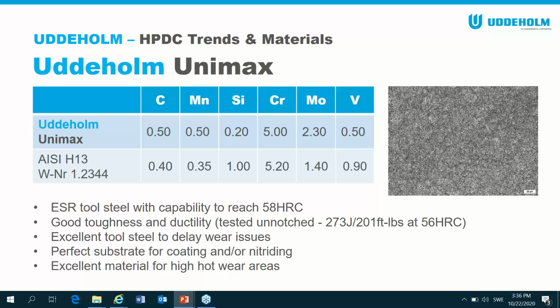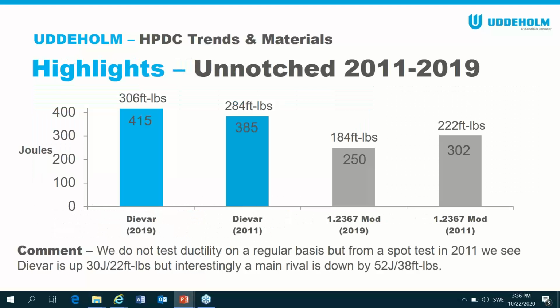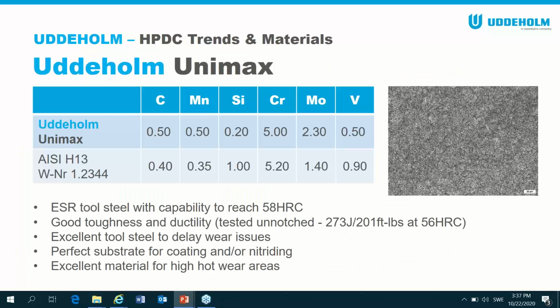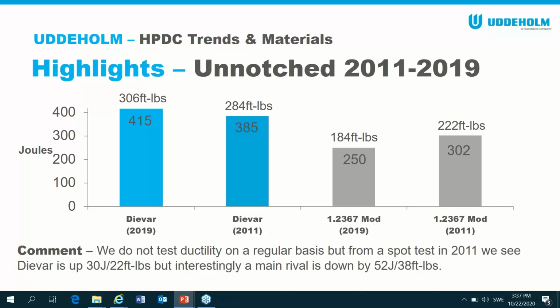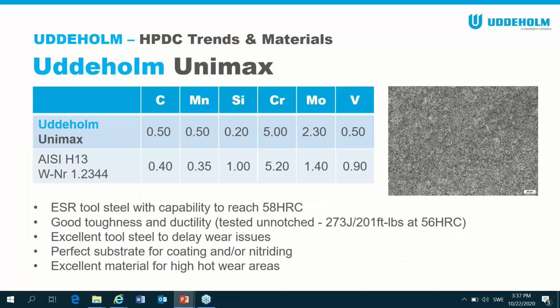Interestingly, we tested it this year in a forging application at 58, 56 Rockwell, and we got 201 foot-pounds in an unnotched test, 14 joules in a V-notch. And if you think, well, where does that sit then, Richard, if you ask me? Well, actually look at the 2367. So we've got here 201 foot-pounds, and in 2367 we've got 184, 222. So Unimax is probably somewhere in the middle of that, depending on the quality of the 2367.